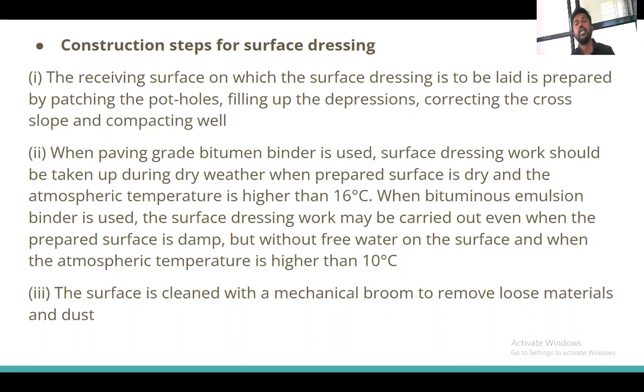When paving grades of bitumen binders are used, the surface dressing work should be taken up during dry weather, when the prepared surface is dry and the atmospheric temperature is higher than 16 degrees Celsius. Also, when we apply the surface dressing layer, we should think about the temperature around it, because temperature will also affect. So we have to ensure that the temperature is higher than 16 degrees Celsius when the bitumen is to be applied.